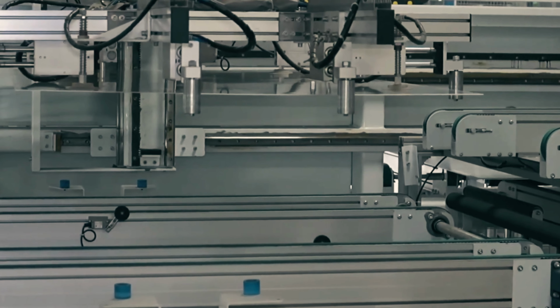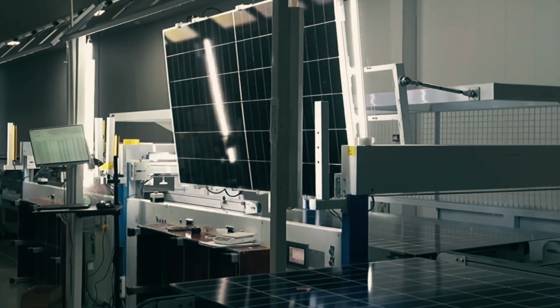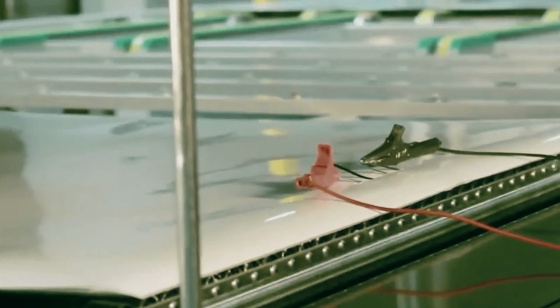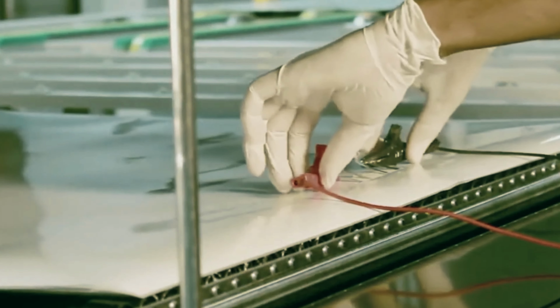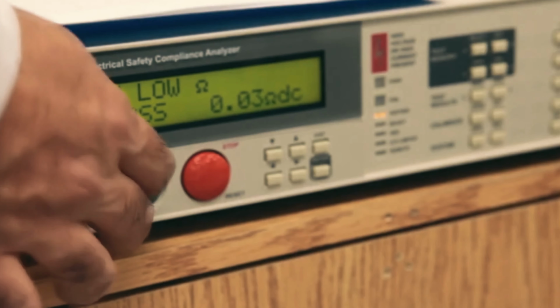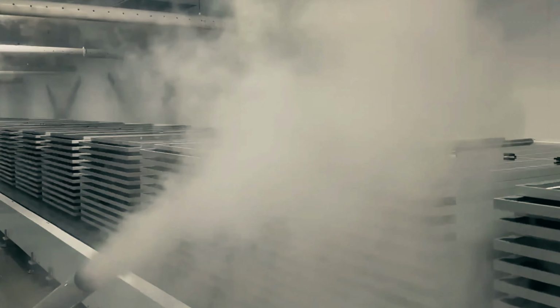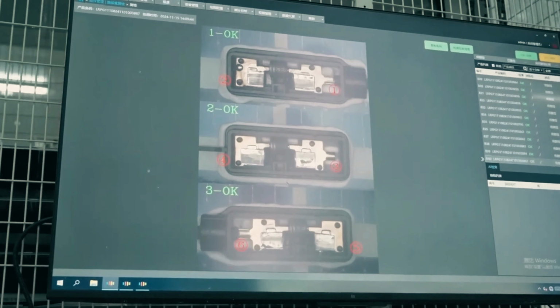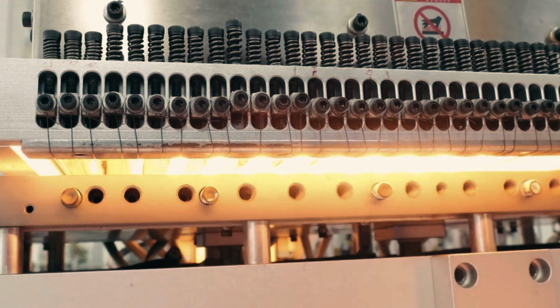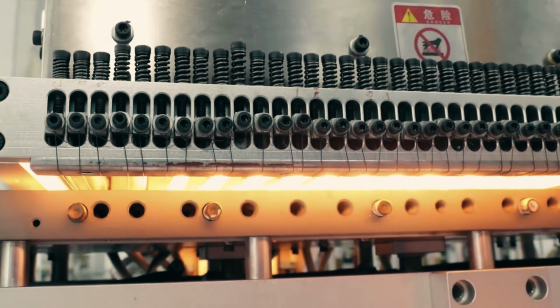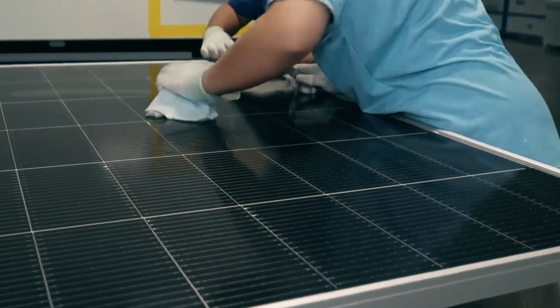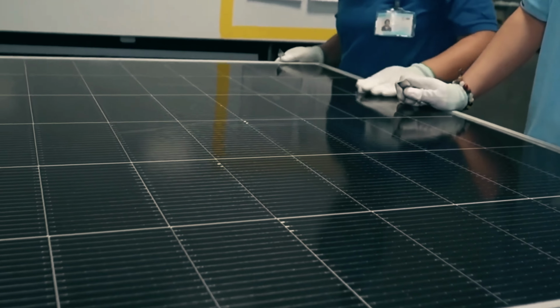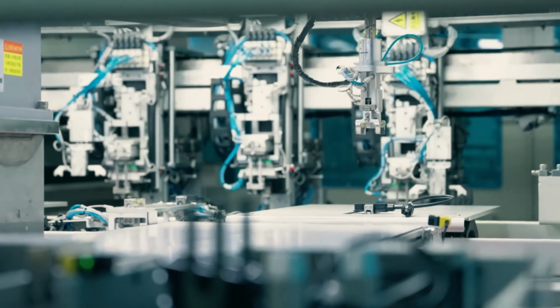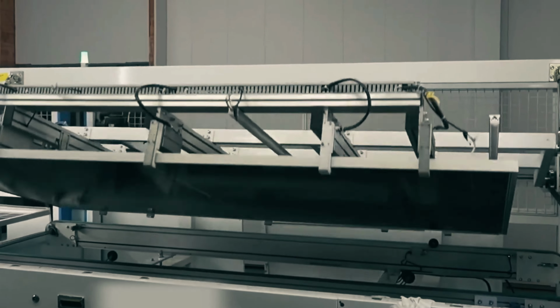Before a panel design is ever approved for mass production, sample units are pushed through a gauntlet meant to compress 25 years of weather into a matter of weeks. Panels are baked at extreme heat, then flash frozen, cycled back and forth hundreds of times to check whether the glass, metal frame, and internal layers expand and contract at compatible rates. Others are blasted with simulated hailstones fired from an air cannon, soaked in humidity chambers to test whether moisture can creep past the seals, and mechanically loaded with the equivalent of heavy snow to confirm the frame won't buckle.